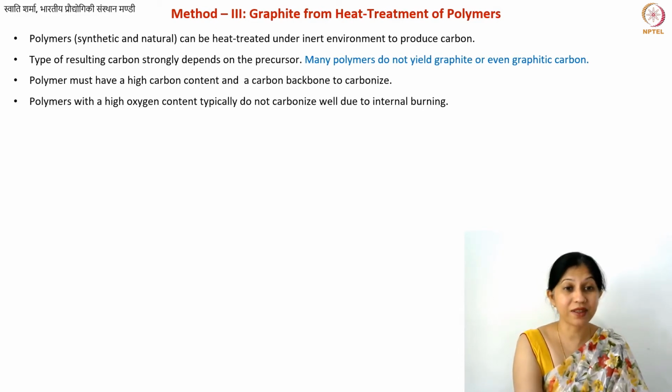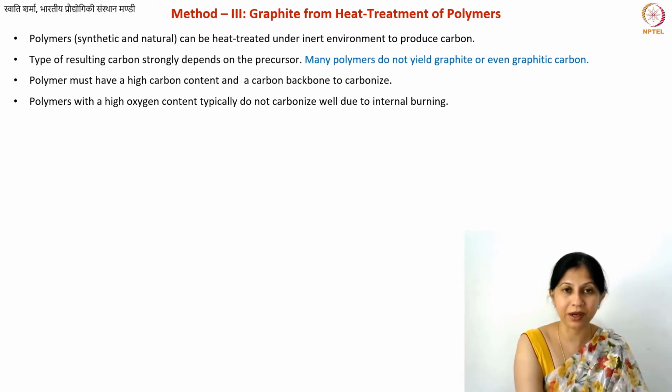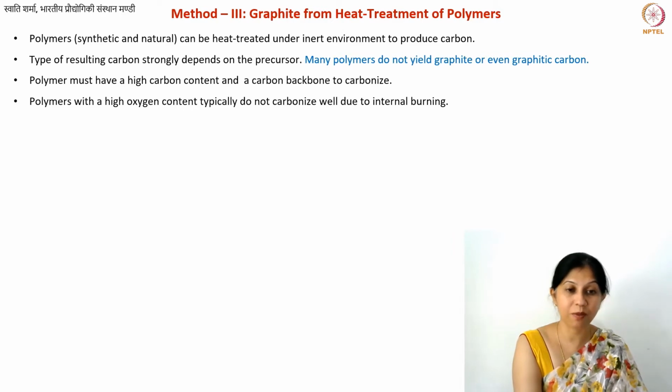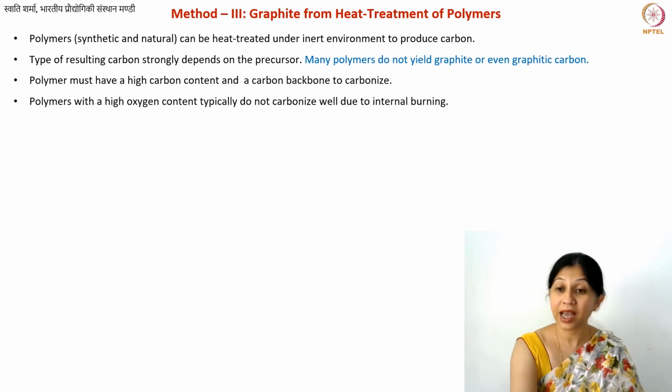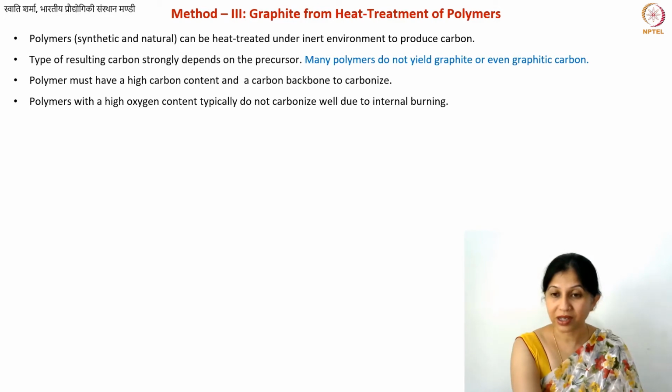But in the case of some polymers, you can say that you'll get some carbon, but whether or not it will be graphite, that is hard to say without experiments. But in principle, if your polymer is already semi-crystalline, which means it already has some layered arrangement, and if it has reasonably high aromatic content, then you might be lucky and get graphite out of it. Okay.